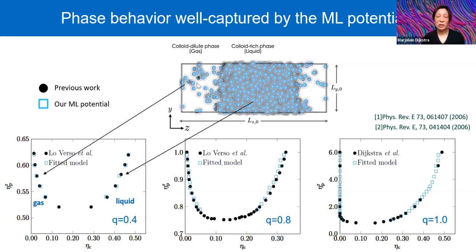So here we find phase separation between a colloidal gas and a colloidal liquid phase. The colloidal liquid phase is dense in colloids, and we can measure the density. The colloidal gas phase is very dilute in colloids, and we can also measure the density there. And then we plot all the binodal points as a function of the polymer concentration along the y-axis and the colloid packing fraction along the x-axis. We can again compare that with previous work, and we find that the gas-liquid binodals are really well captured by these machine learning potentials with respect to the full binary calculations. And this is for different size ratios. If we go from left to right, the many-body interactions become more pronounced because the polymer coils become bigger in that case.